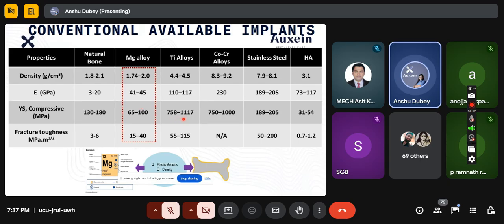So what does this lead to? This will lead to many problems, and that is why it is the major concern with these conventional metallic implants which are available in the market and people are using. There were a lot of problems dealt with these conventional metallic implants. But on the other hand, if you see magnesium, its density is very close to bone, 1.8. The elastic modulus also follows the natural bone, and the compressive strength is literally very near to the natural bone.